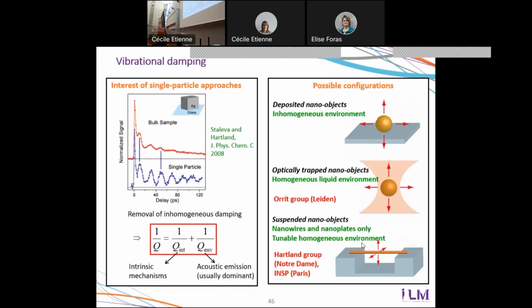So now I want to address a second topic about vibrations of objects, which is that of vibrational damping, which I have just introduced previously to motivate single particle experiments. When you perform such single particle experiments, the damping of the oscillating signal that you see here actually reflects the actual damping of the vibrational modes, and it arises because of two different processes. First, intrinsic mechanisms occurring within the particles, which are not very well known at the moment. And second, the fact that the vibrations of a nanoparticle do not remain forever localized in the particle. They will propagate towards the environment, and therefore acoustic waves will be emitted in the environment, which will reduce the vibrations of the object itself.